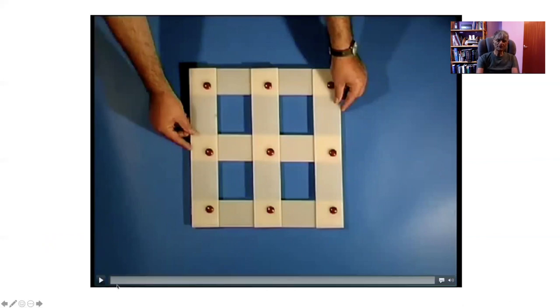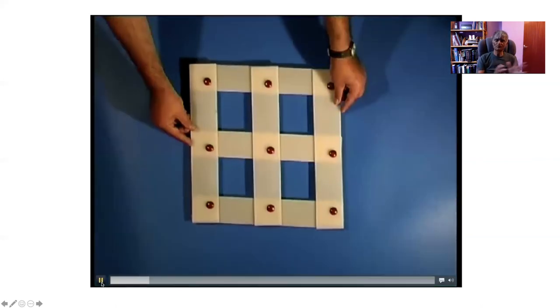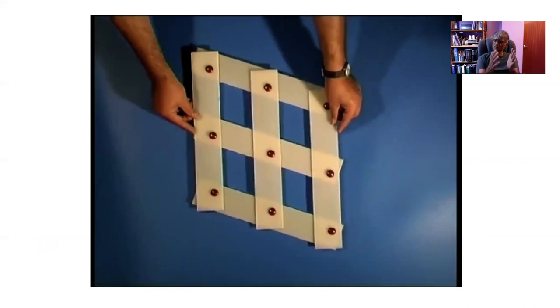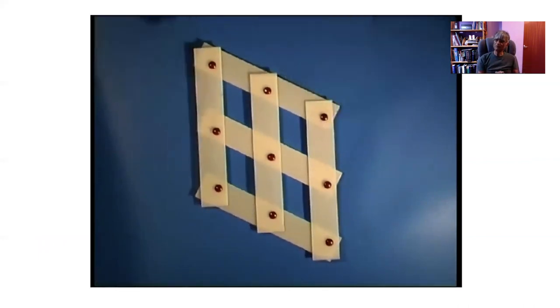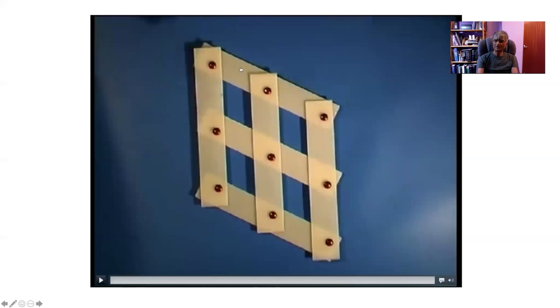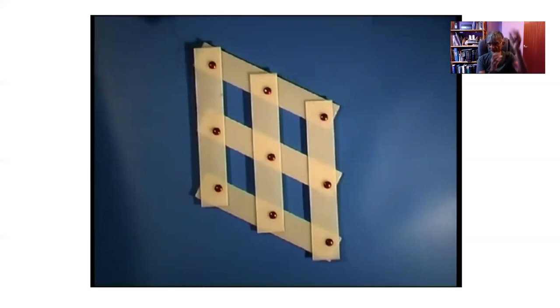I can deform that into a different crystal structure without breaking any of the bonds, okay? So here, this is a homogeneous shear deformation that I've applied, and we now have a new lattice. It has this shape as opposed to the square pattern. And notice also that the macroscopic shape of the crystal must necessarily change in a way consistent with the atomic patterns of the parent and product crystals.